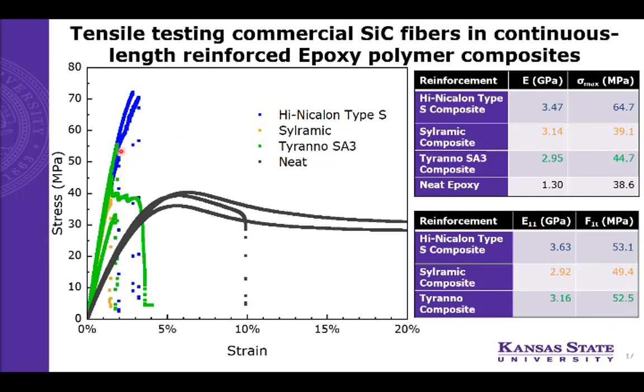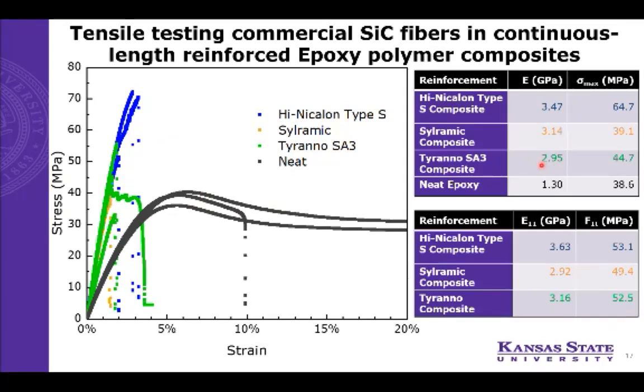But here we can see the experimental data, where we had 3.47 for our elastic modulus on average for Hi-Nicalon Type S, followed by the Sylramic at 3.14 and the Tyranno SA3 at 2.95. However, the fracture strength maximum that we calculated as a theoretical value is slightly lower than our experimental value for the Hi-Nicalon. So there are some questions to be had there, as well as the Sylramic elastic modulus being slightly higher than the theoretical maximum.